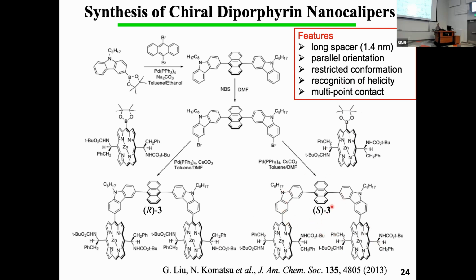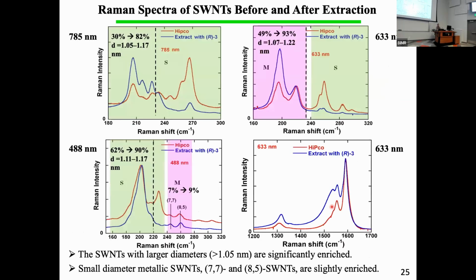And the multi-point contact can be expected, not only the pi-pi stacking, pi-pi interaction, but also the CH-pi interaction at the spacer region. And these are typical examples to compare the carbon nanotube before and after extraction. So this is a Raman spectrum. The Raman shift is somewhat correlated with the diameter of the carbon nanotube. A larger Raman shift means a smaller diameter. A smaller Raman shift corresponds to a relatively larger diameter of the carbon nanotube.